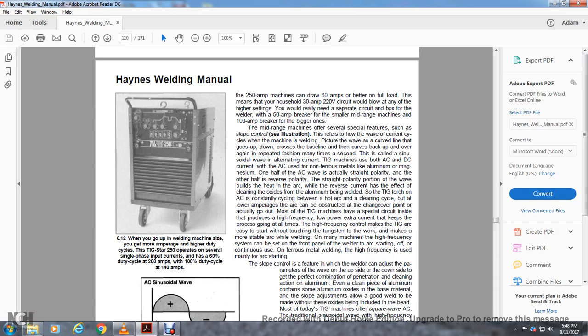On one half of the AC cycle is straight polarity, and on the other half is reverse polarity. The straight polarity portion of the wave builds the heat of the arc, while the reverse current cleans the oxides off the aluminum being welded. So the TIG torch on AC is constantly cycling between hot arc and clean cycle, but at lower amperage the arc can be interrupted by the current crossing over the point and going out. Most TIG machines have a special circuit inside that produces a high frequency, low power extra current that keeps the process going all the time.